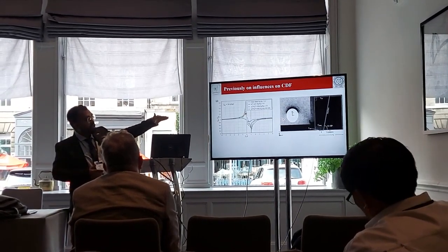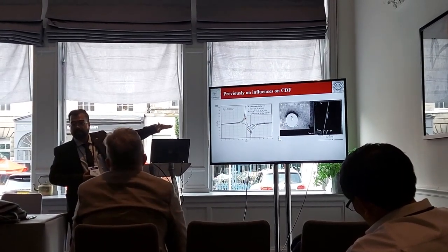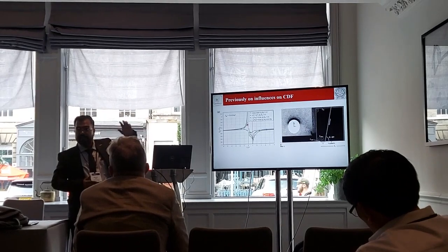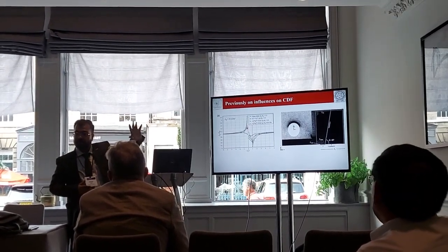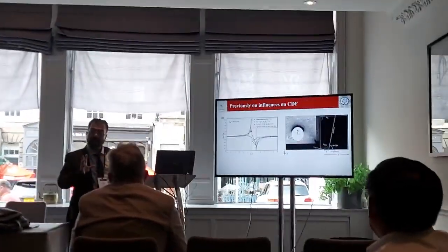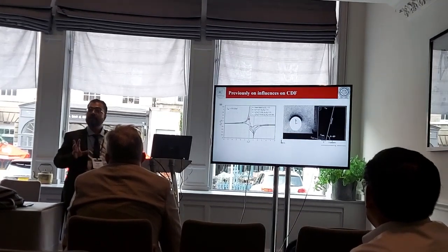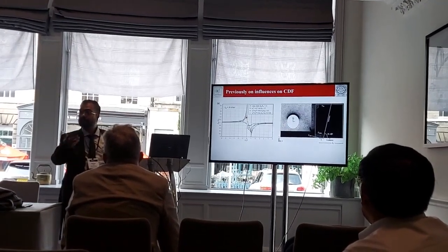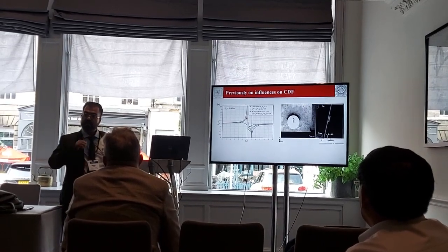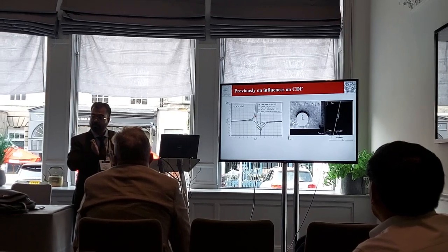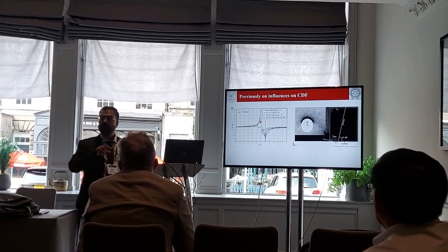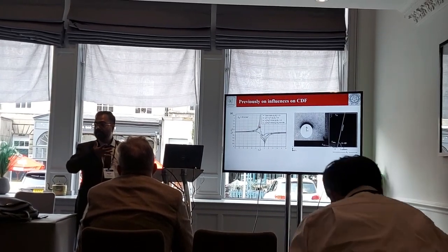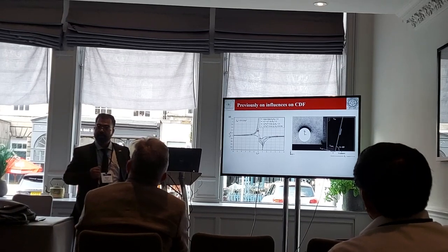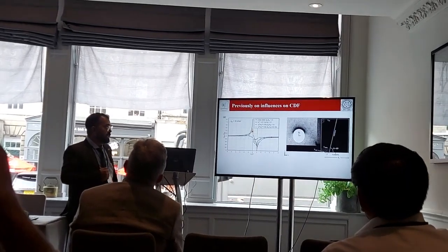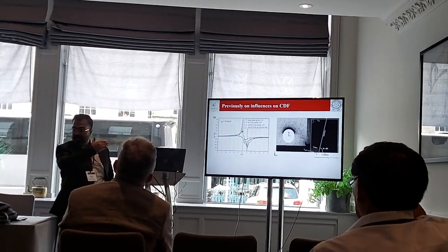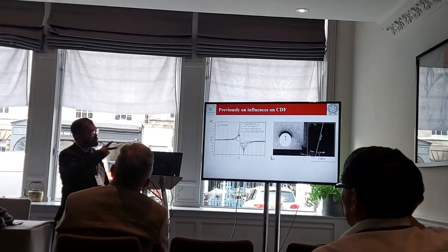What happens is, when the crack comes closer to the first interface, the crack driving force is increasing. That means the crack is getting attracted towards the first interface. For the same amount of energy which you have supplied to the specimen or to the component, the crack will have a tendency to grow faster and come closer to the interface. The reverse will happen when the first interface is crossed, so it is broken, and it faces the second interface where the reverse transition is happening. So it is going from a stiffer to a compliant material, so from high yield strength to low yield strength material. In that case, the crack driving force drops down in the interface, and that's the interesting point. So the scenario will be reversed.